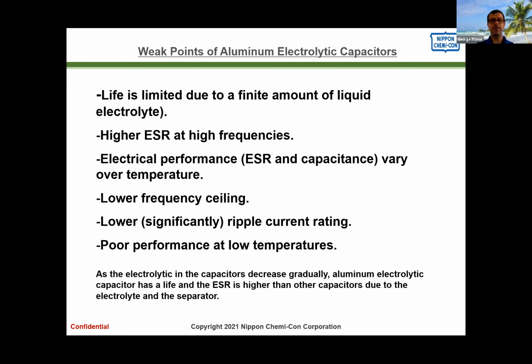You have a significantly lower ripple current rating. Some of that is due to its higher ESR, and some of that has to do with the fact that you have a certain life target you're trying to meet. So having a higher ripple current rating will translate into more internal heating and a shorter life. And I mentioned earlier a little bit about the low temperature performance, which is not a defect, but it is something to keep in mind.